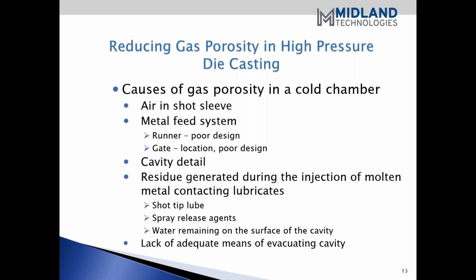And then the next contributor would be the residue, and that residue, of course, occurs when any residue that's left on the surface of the cavity or the runner or any part of the metal feed system comes in contact with the metal that's injected. So our shot tip lube can be a contributor. Spray release agents remaining on the surface, overspraying can be an issue. Water remaining in the cavity, and then the lack of adequate means of evacuation.